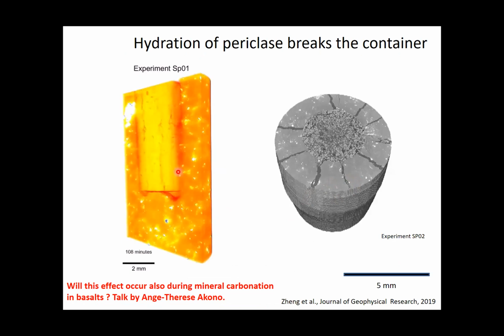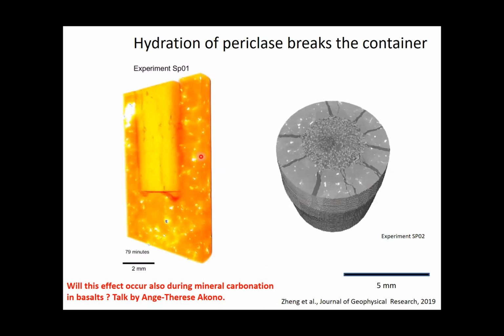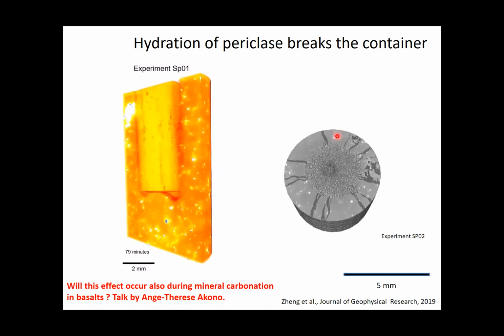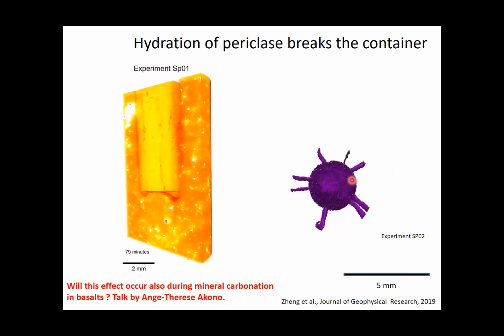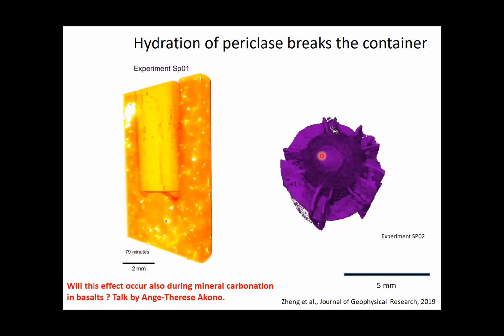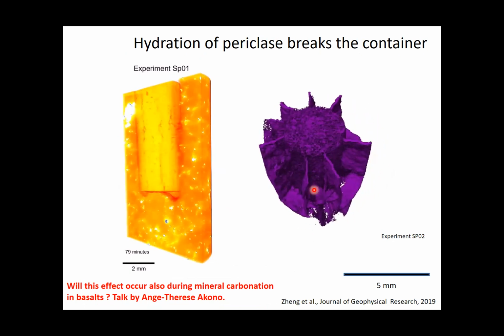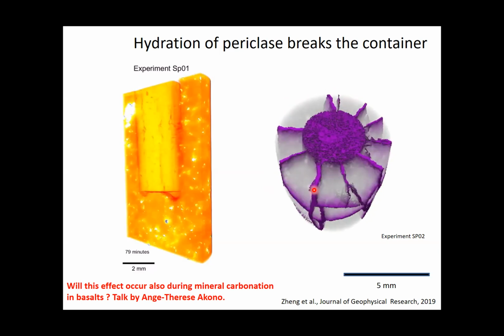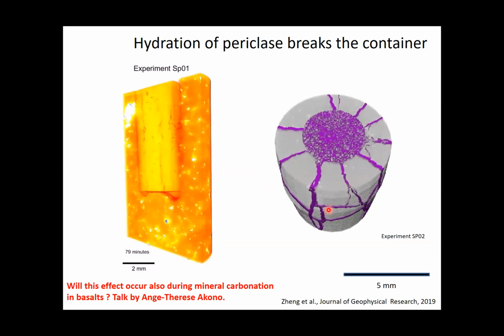We get this, just a slice view of the sample through time. The periclase here in the middle will start to react and produce brucite. So brucite appears here in dark orange. And at some stage, this brucite will exert a force and start to break the container. We can see fractures, and that's the shape of the container at the end, where part of the periclase in the center has been transformed, and a fracture network has formed in the rock container.